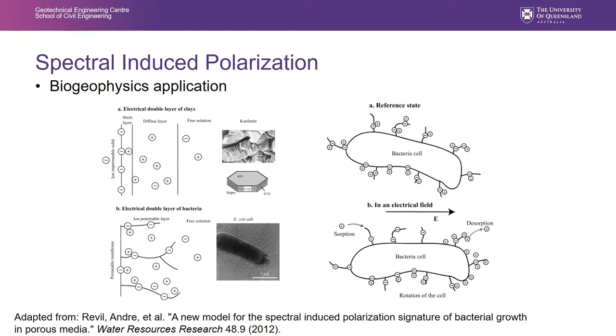And finally, we've started to investigate this biogeophysics application because once again, the electrical double layer for clays has a very strict and very defined structure. But if you consider bacteria, you'll have a brush-type electrical double layer structure, which means that you will have a different signature in the low frequency range. And if you apply an electric field, the way the bacteria polarize is very different. So this is very new research. The first measurement was done in 2012, and this is what we would like to investigate. For example, for tailings, especially if you use bio-leaching to consume the metallic content, we should be able to monitor the metallic content over time thanks to this spectral induced polarization.